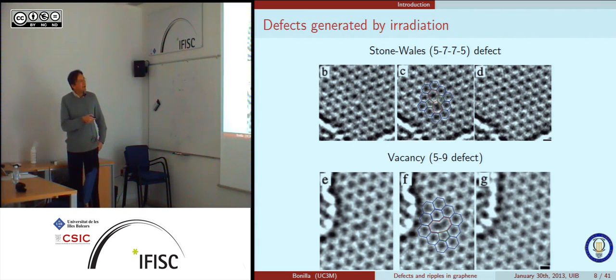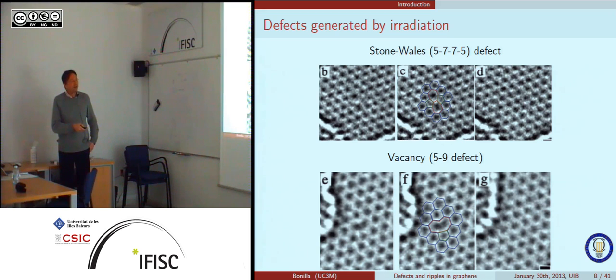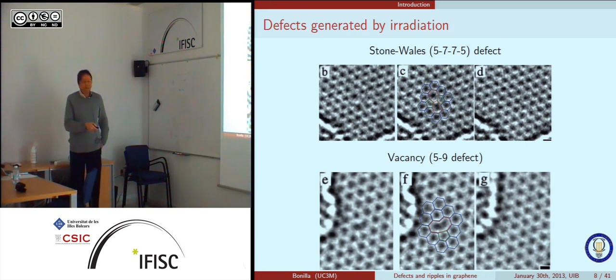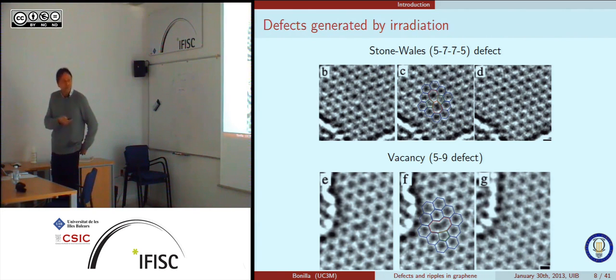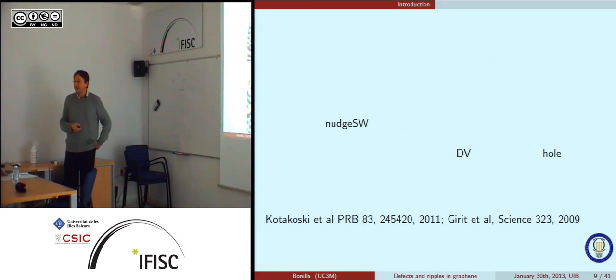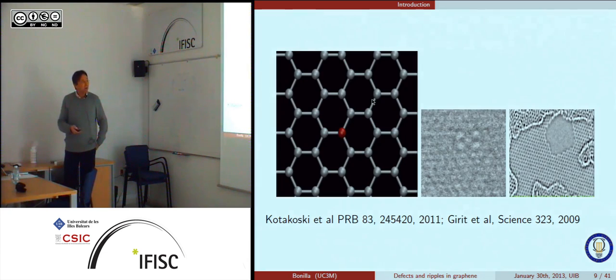This is another one. You see the resolution here is not so great, so they needed some software to superimpose a lattice here and discover what kind of defect it is. So this is another defect. There is a carbon atom missing, and what you get is a pentagon and a nonagon defect. Of course, this one also disappears after a while, but not because the bonds rotate back and you get the pristine lattice, but because there are adsorbed carbon atoms, and one of them falls into the vacancy and fills it, and that's it. Anyway, the time scale for all of these changes is extremely long, of the order of seconds.